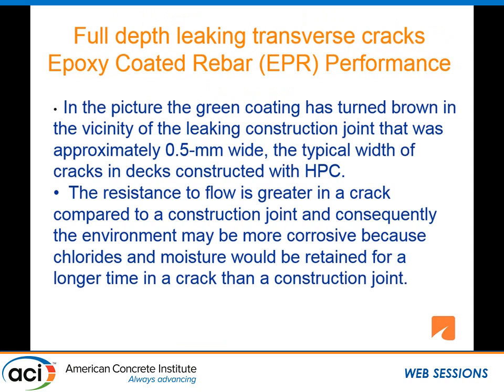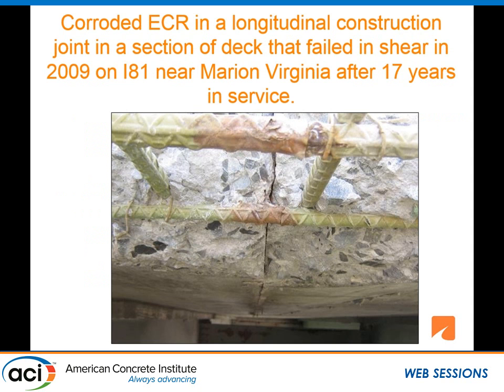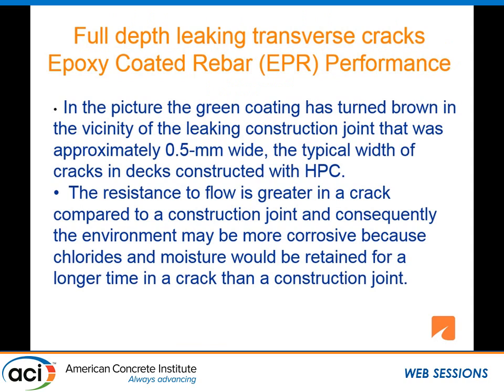In the picture, the green coating has turned brown due to exposure to moisture and chlorides, wetting and drying cycles. The crack, in this case the construction joint, is about 0.5 millimeters wide, which is typical of the full-depth cracks we get in the high-performance concrete in our decks now, which are leaking.